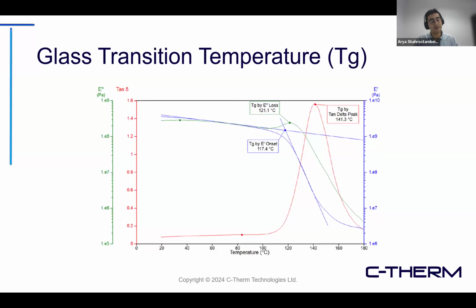And the loss modulus is the closest one to what the DSC method uses to obtain glass transition temperature. The principle is different, but that's the closest approach. And the tan delta method, which is the most sensitive one, is used by DMA, and it's called the mechanical approach. And as you can see, there is a significant difference in that temperature. So it is important to have reliable information on that temperature, based on the different behavior of the material that I mentioned before.